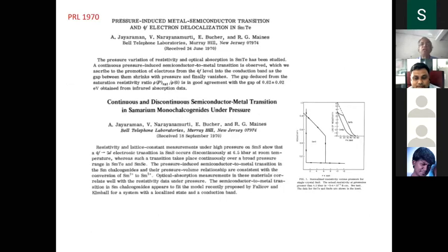Now, the field got developed further when Jayaraman, who was actually a nephew of Sir C.V. Raman, and was at Bell Labs, studied chalcogenides, samarium sulfide and telluride. He found that samarium sulfide behaves exactly like cerium metal. When you apply pressure, as a function of pressure, you could find there's a volume collapse here. Your resistivity drops suddenly at some pressure, something like 6 kilobar, 6.5 kilobar. There's a first order transition. There is hysteresis here.